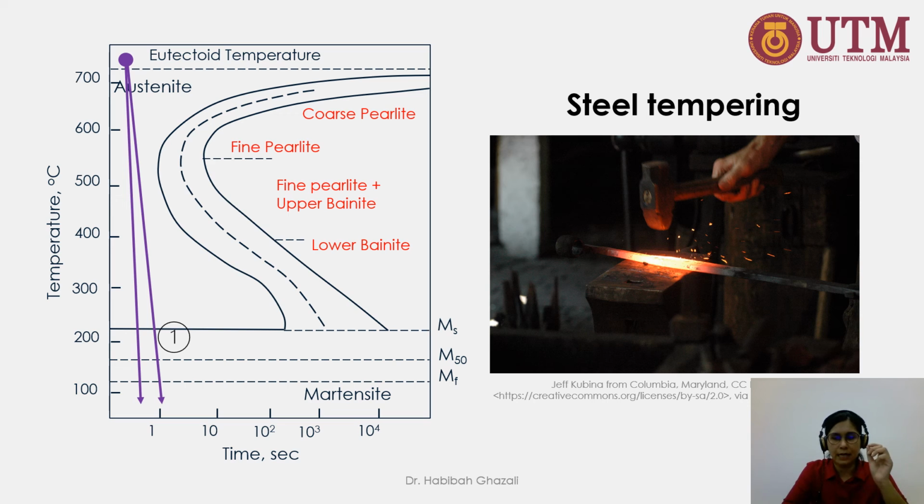But at the same time, the BCT microstructure of martensite does not have a slip plane, so we have a material with very high brittleness. If we look at people sword fighting, the steel does not break straight away, so there must be a second procedure. The second procedure is that the blacksmith will temper it at a certain temperature above the martensite start formation.